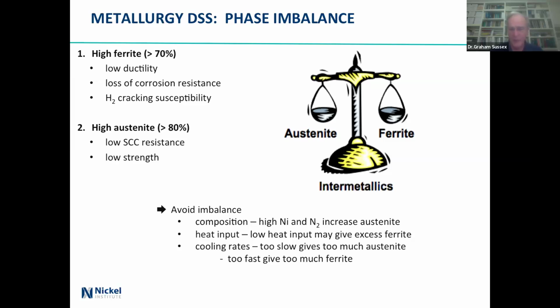Heat input: low heat input is likely to give excess ferrite because it'll cool down very quickly. It doesn't get time for the austenite to form. And cooling rates: if they're going down too slowly, then you'll get much too much austenite. Too fast, too much ferrite. And in the middle, you get the intermetallics.